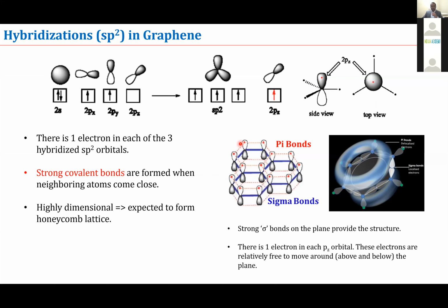So this constitutes the electronic cloud. Because these electrons do not collide when you apply an electric field, and these electrons try to transport because of the application of the electric field, they do not encounter the ion cores. They can transport like a fluid. So therefore you can expect very high conductivity, and that is why graphene has very high mobility, which is about 100,000 centimeters square per volt second, which is very high.